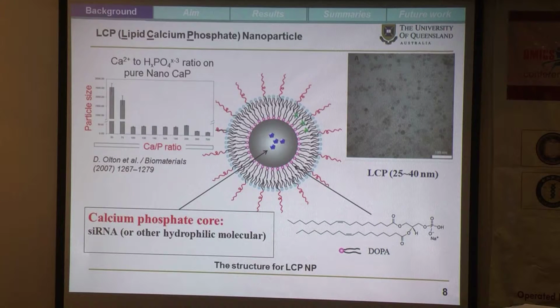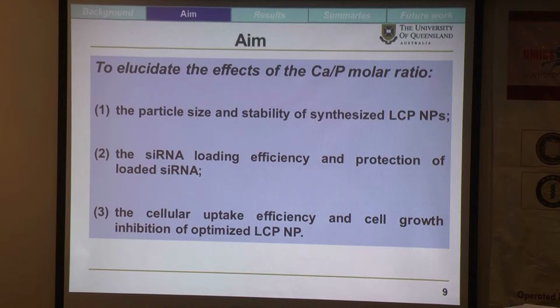Previous studies indicate the influence of the calcium to phosphate ratio on the pure nanostructured calcium phosphate nanoparticles. While it is unclear how the calcium to phosphate ratio will influence the properties of the LCP nanoparticles in the presence of the DOPA, because DOPA may substitute part of the phosphate group on the surface. So in our study, we aim to elucidate the effect of the calcium to phosphate molar ratio on the particle size and the stability of the synthesized LCP nanoparticles,